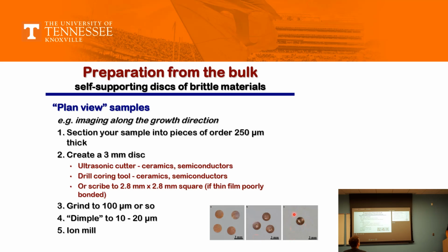This is something that we do every time at Oak Ridge National Lab. We take this small specimen and we dimple it. After dimpling, we can either electropolish it, or there is another technique, ion mill, that we used in the past. Has anyone heard about PIPS? No? This is another tool that most labs used to have during my PhD. It uses an argon ion beam that simply mills the center of these dimples. So ultimately you have this thinner piece that would be given to you.